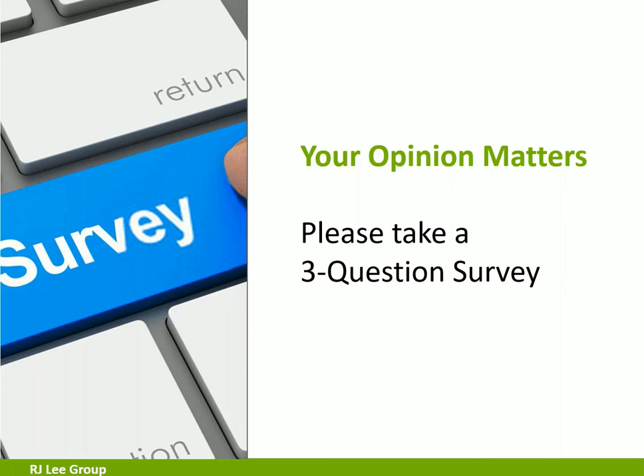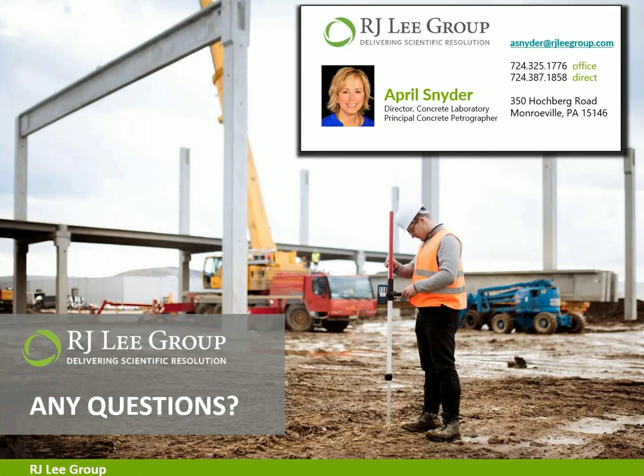Okay, thank you. Here's another question for pyrrhotite. Is it RH of the concrete or the local humidity of the environment? It would be RH of the concrete. And what we've been seeing is there seems to be a sweet spot. Some people may think that you really need a lot of water to get this reaction going, but it really is the oxygen that drives the reaction. And there seems to be a sweet spot. Don't quote me on this, but between like 50 and 70% relative humidity has been the highest damage.